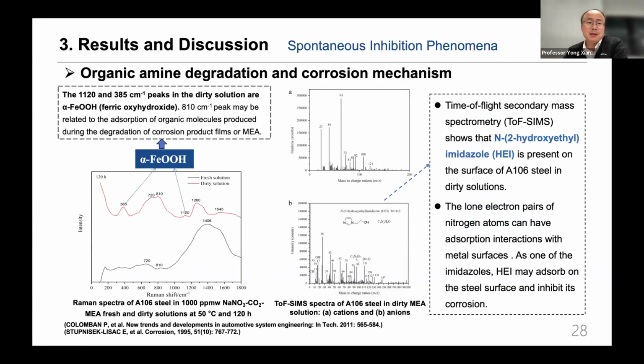We also did some film characterization and found some products like ferric oxyhydroxide. On top of that, we found some degradation product on the surface. That is hydroxyethylimidazole, HEI, which is a kind of MEA degradation product. So we think maybe the HEI adsorbs on the surface of the coupon, and then it reduces the corrosion rate of the A106 steel.